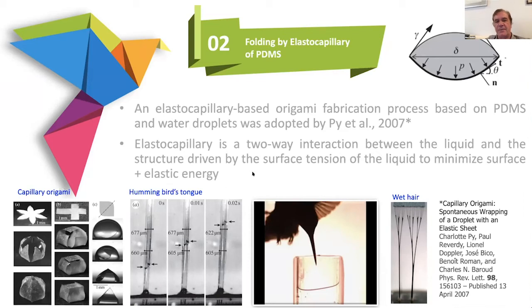The forces involved are elastocapillary, which is a two-way interaction between the liquid and the structure, driven by surface tension of the liquid to minimize surface and elastic energy. In a way, you can see this phenomenon when you come out of the bathtub, where your hair strings together with the water droplets and takes on shapes surrounding the water droplets. It's also the way a hummingbird takes honey out of this vessel here. The tongue is split, opens up around the honey, and then is pulled back, as you can see here. So those are the forces that this group, Py et al., was using to make these PDMS structures.